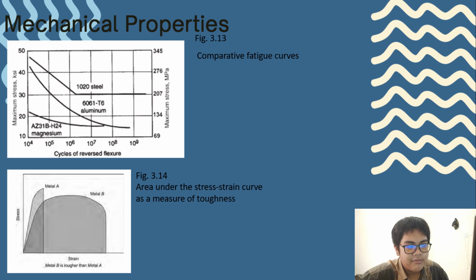As we can see, the amount of ductility is also related to the toughness of a material. For the static or low strain rate situation, toughness can be determined from the result of a tensile stress-strain test. It's related to the area under the stress-strain curve up to the point of fracture, figure 3.14. As we can see, metal B is tougher than metal A. Area under the stress-strain curve as a measure of toughness.